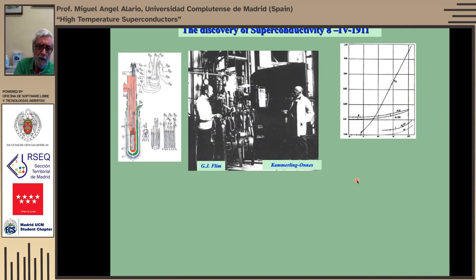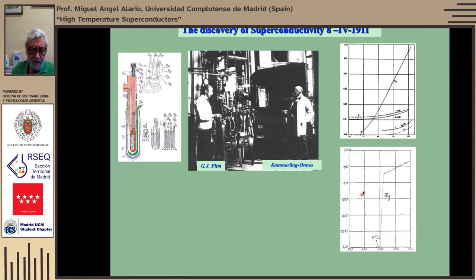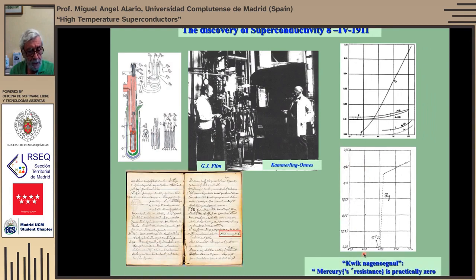So with this, he actually was able to measure, as we said, the resistivity of several metals, and you see that mercury already shows pretty well that it is different from the others. You can see it goes down, and then we have this little bit here that if we can get it big, the resistivity actually disappears. So in his notebook, he mentioned that the mercury resistance becomes practically zero. So this is when superconductivity was discovered, and then he actually invented the word, and he became a very interesting person in science and in the history of science. This is really a remarkable discovery.